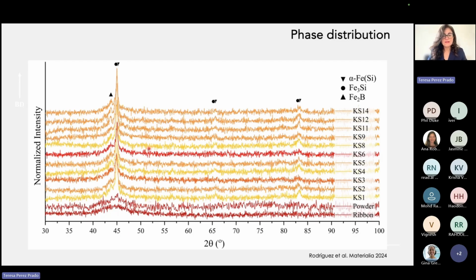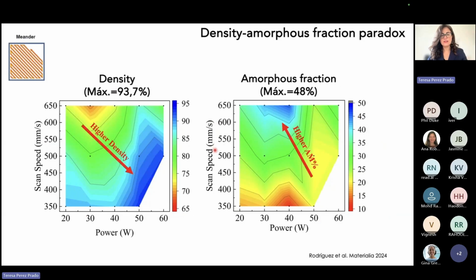And all the other patterns that you can see there, they correspond to all these what we term KS samples. It doesn't matter. These are all the samples that are included within the region of the processability window where we could get nicely shaped cubes. And as you can see in all of them, we seem to have this wide peak at 45 degrees, but very clearly we have crystalline peaks. So in all this window, with the commercial alloys, with the simple scanning strategy, we always get a composite material, an amorphous crystalline composite. It is impossible to make a fully amorphous material.